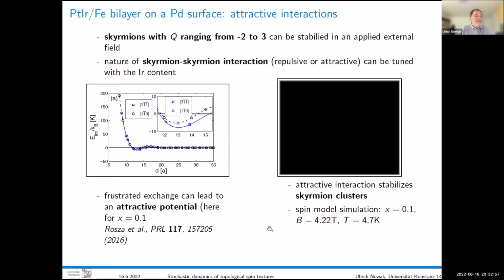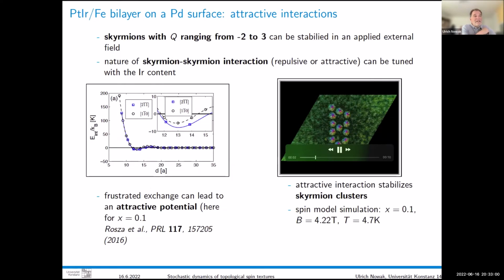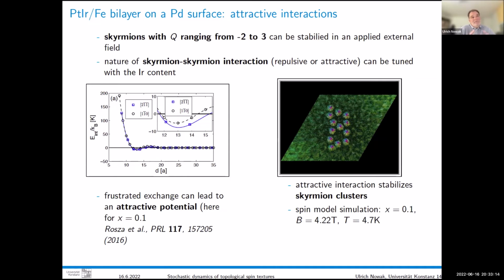And that leads to the fact that you can stabilize skyrmions and other skyrmionic structures with a topological charge ranging from -2 to 3. I will show you that later on a slide. And they can all be stabilized depending on an applied external magnetic field. And then in computer simulations, you can investigate their behavior. You can also calculate the skyrmion interaction, which can be attractive. That is rather unusual, but in that model system here, it can be attractive, as shown in this paper. And then you get clusters, even clusters of skyrmions like that. But I will not talk about clusters in the following, but individual skyrmions and their behavior.